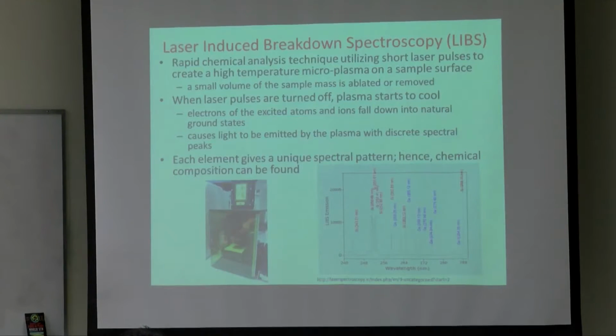And so a plasma is just a charged region, a charged gas. So you have a bunch of charges and very high temperatures. They've been observed to have temperatures as high as 30,000 Kelvin, which is extremely high. So when the pulses are hitting the surface and creating this ablation, eventually you turn off the laser pulses, and the plasma starts to cool off. Thinking back to our energy states, you're exciting all these electrons to high energy states, and when you turn off the source of the agitation, they start to go back into their ground states, or where they want to sit down.